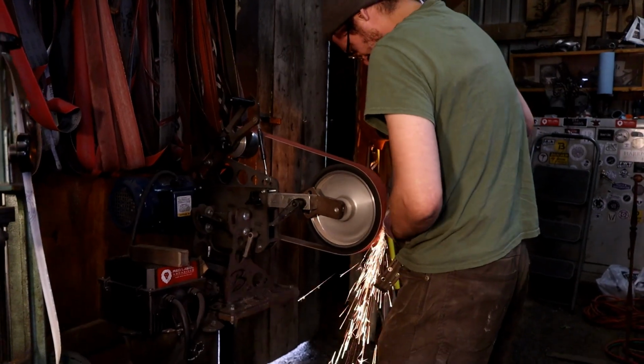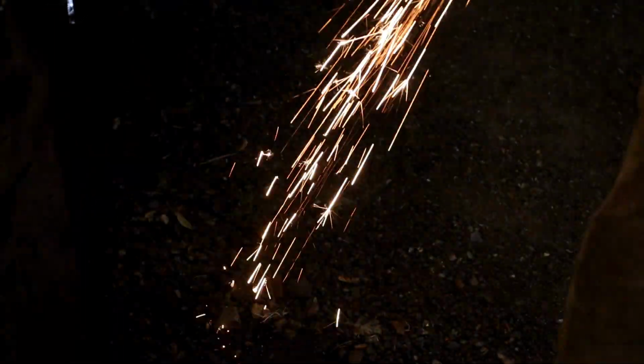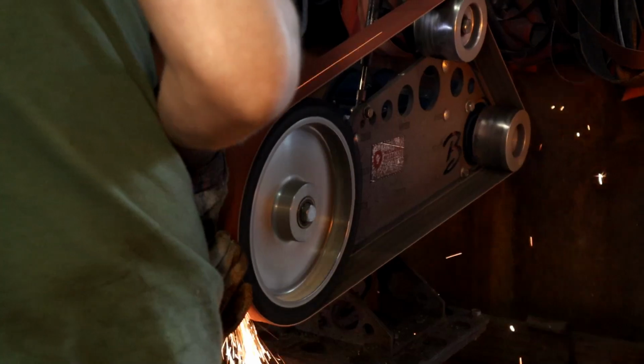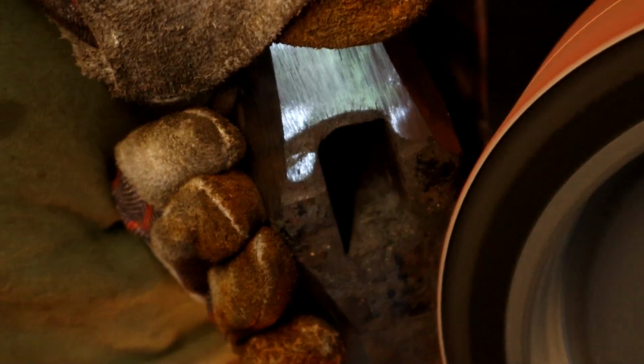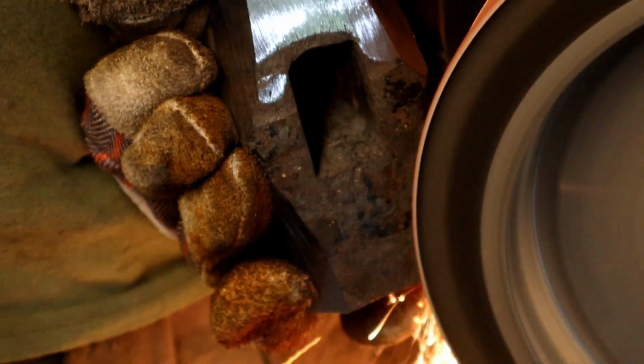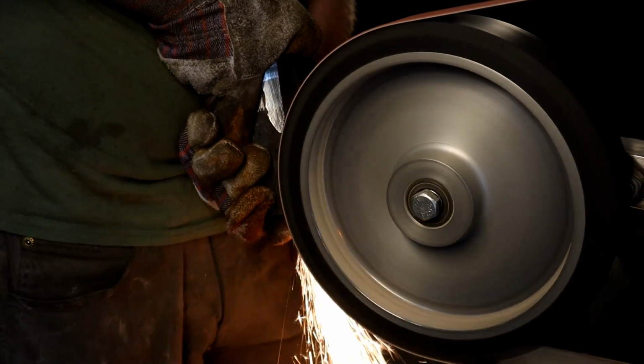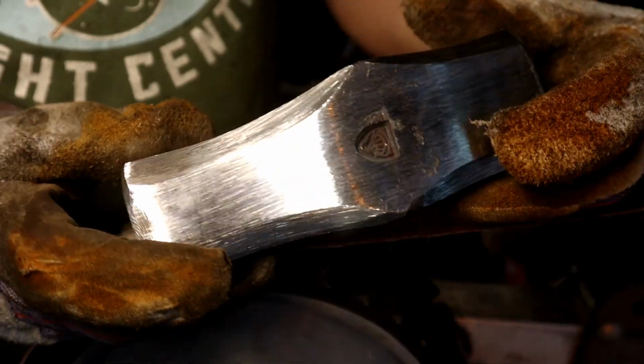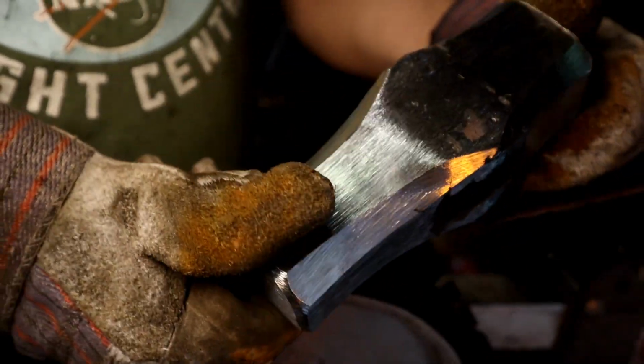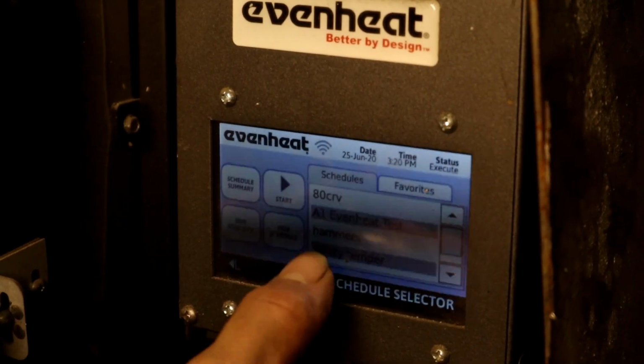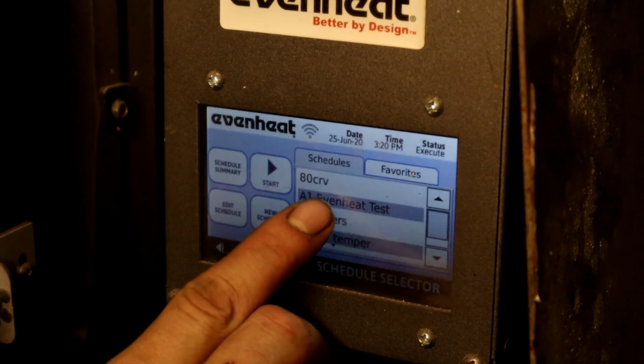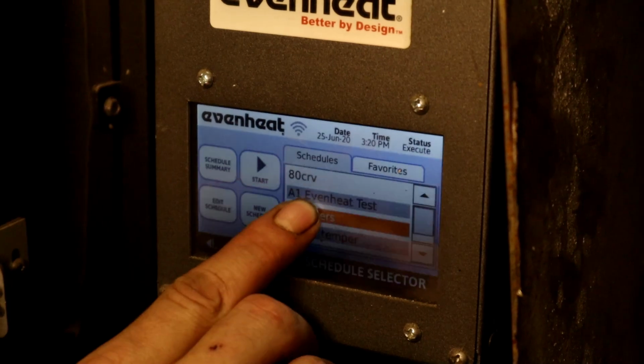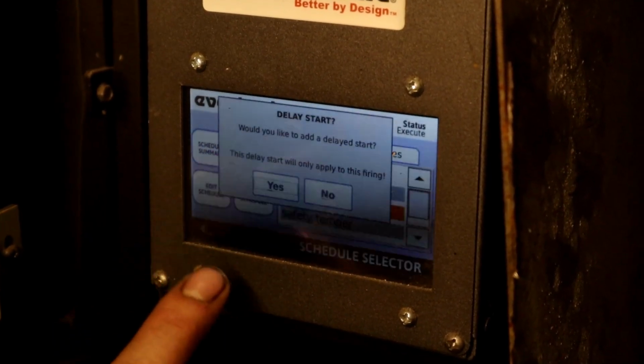You may notice during the grinding we're only using a 36 grit belt before heat treating. That is done on purpose. Using a 36 grit to scratch in on the surface of the hammer helps it add surface area, ensuring a better quench during the heat treat. Before placing the hammer into the forge to heat it up and then quench, we first turn on our even heat kiln to get ready for the tempering after the quench.